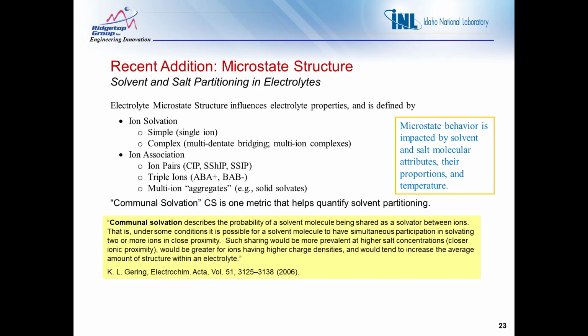So we had a recent addition of a new calculational platform within AEM, and this covers microstate structure. So essentially what that is, is solvent and salt partitioning within the electrolytes. This is driven primarily by behavior due to ion solvation, whether it's simple or complex. Simple meaning single ion, complex meaning multidentate type bridging, and multi-ion complexes being solvated. Also contributing to the microstate structure are things like ion association. So there are different combinations of ion pairs, triple ions, and more complex aggregates that can appear as you add salt to a particular choice of electrolyte solvents. And this is very much tied into the attributes of the solvent and salts, as well as things like temperature and also the proportion of all the different components.